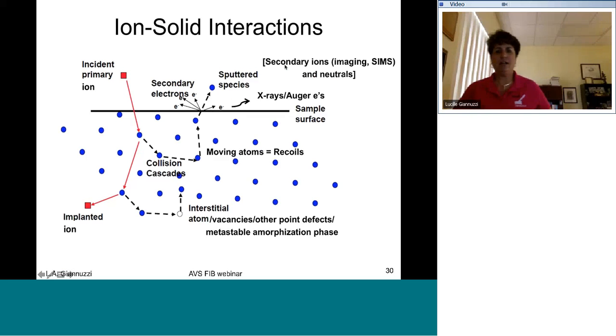And then you can also get secondary ions, and these secondary ions can be used for imaging or also for secondary ion mass spectroscopy or spectrometry. You can also get, of course, neutral ions. So basically, if you think about it, we can control which types of species we get by controlling the ion type, the ion mass, the ion energy, and also the ion incident angle. And what also affects what's going on here, of course, is the solid that we use, the target. And what we don't see here is that the target crystallinity can also affect what's going on with the ion-solid interaction.